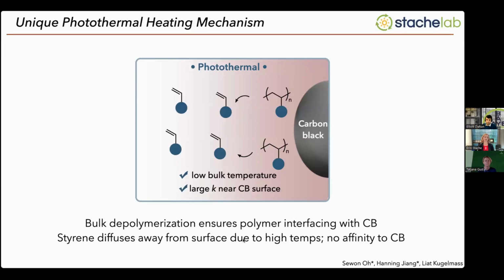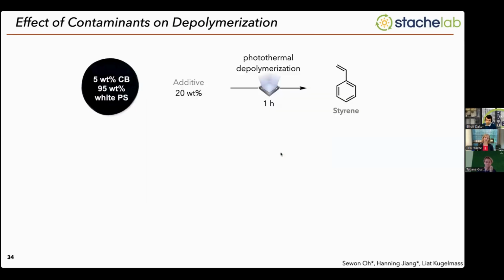depolymerize this mixture. And the reason we think this works, you might think, okay, if the bulk temperature is lower, why don't we see repolymerization of the styrene into polystyrene? And we think it's because the polymer is in close proximity to the carbon black. They're both in solid phase. The carbon black heats up, it starts to break down the polymer, generates styrene monomer, but it's so hot near the surface of the carbon black that the styrene monomer is quickly expelled away from the reactive functional groups on the polymer. And so that's why we don't see repolymerization, even though the bulk temperature is much cooler than near the surface of the carbon black.